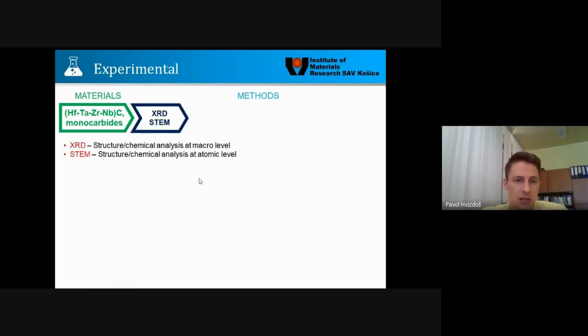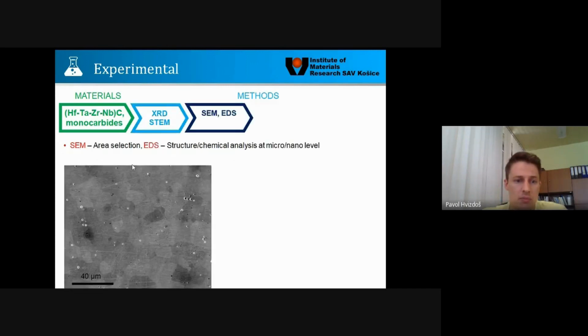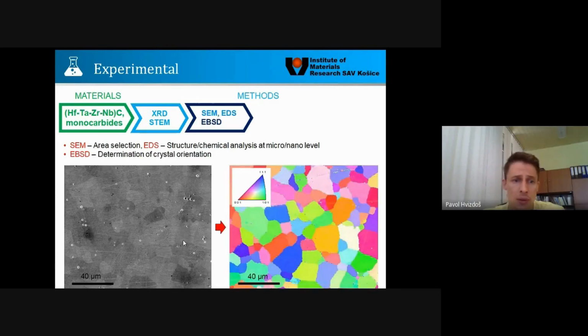After synthesizing the samples, we did structural analysis using XRD and STEM. We did scanning electron microscope to check the surface, to select some specific areas for the testing, and also at the same time we did structural analysis, chemical analysis at micro level and also at nano level. To know the orientation, we performed EBSD, the so-called electron backscatter diffraction, to determine the crystallographic orientation of the grains.